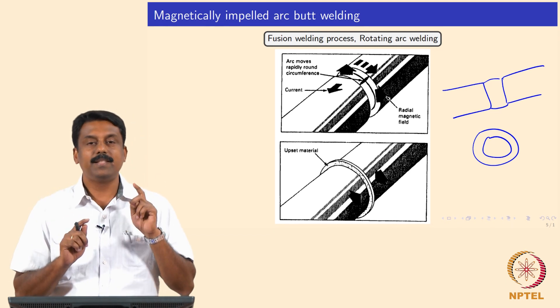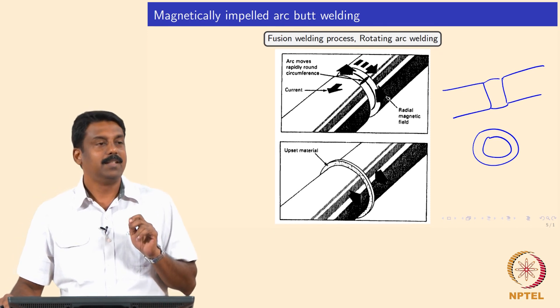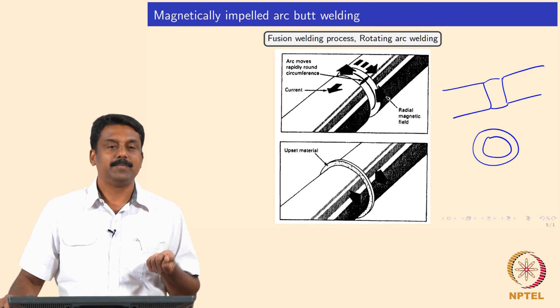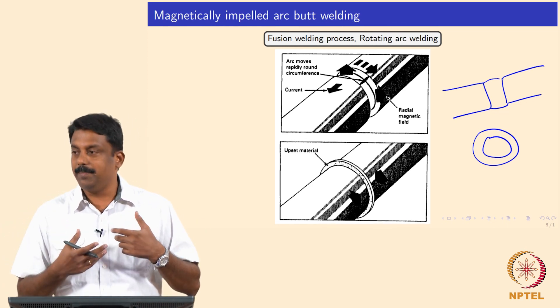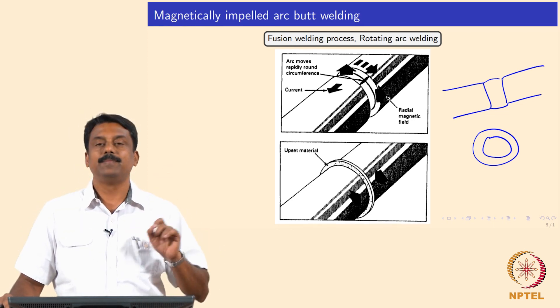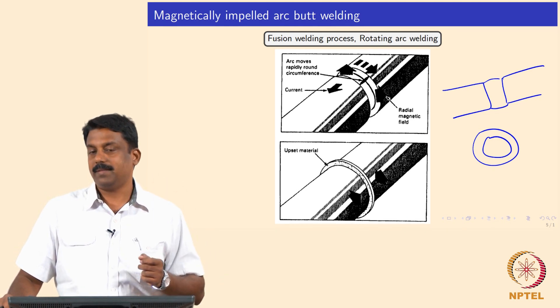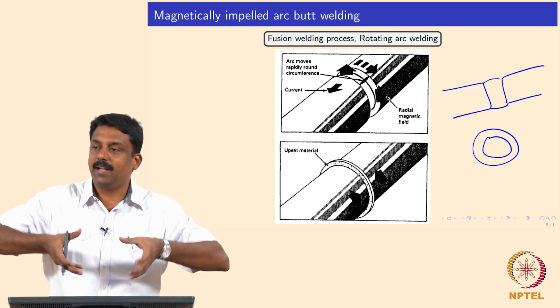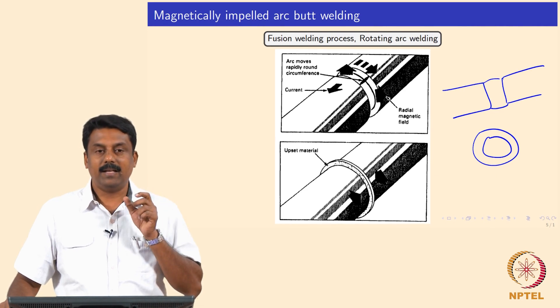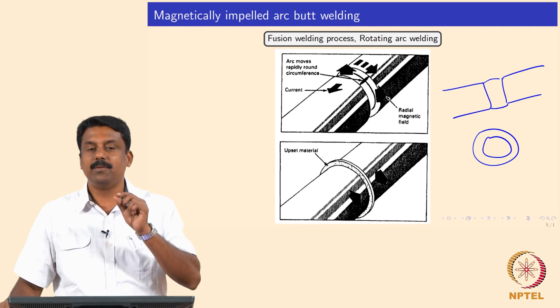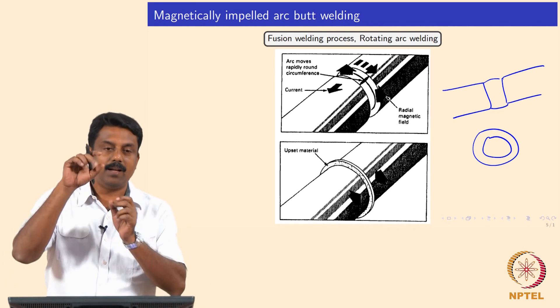So how do you make sure that the arc is struck or travels throughout the cross-section thickness? We have some tricks because this arc can be deflected by a magnetic field. By attaching very strong magnets surrounding the weld job - in this case pipes - the arc can be impelled or deflected throughout the cross-section and also made to rotate through the circumference of the pipe using a strong magnet surrounding the pipe. Otherwise you would never heat the entire cross-section. For flash butt welding it is okay because the thickness is very small - 2 mm or 3 mm - but if you want to weld a 20 mm wall thickness pipe, there will be a strong temperature gradient because the arc will be struck only at the surface.